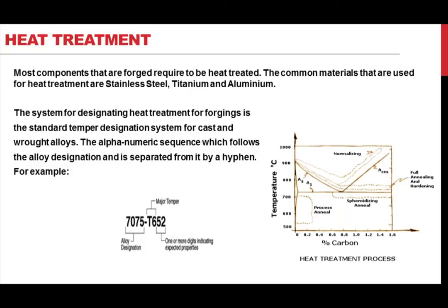Forgings are generally heat treated in the same processes that are used for castings and weldments. The need for heat treating is sometimes eliminated by using an alloy that develops the required properties in the as forged condition. For example, microalloyed steels are sometimes used to reduce or eliminate heat treating operations that would be required for carbon steels. However, the purchase price of forging stock is higher and some additional costs may be incurred due to requirements for additional air cooling equipment. The optimum combination of alloy and heat treatment is best developed in discussions between the forger and the purchaser.